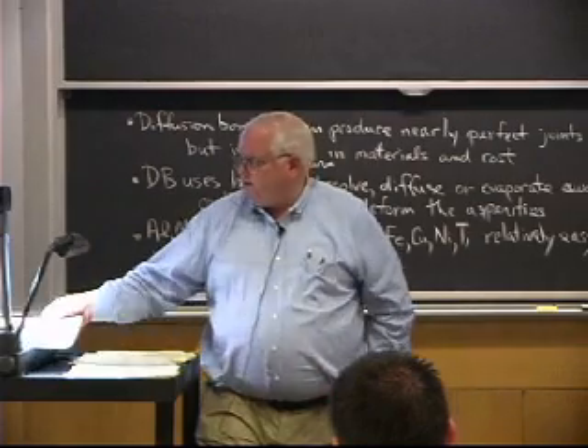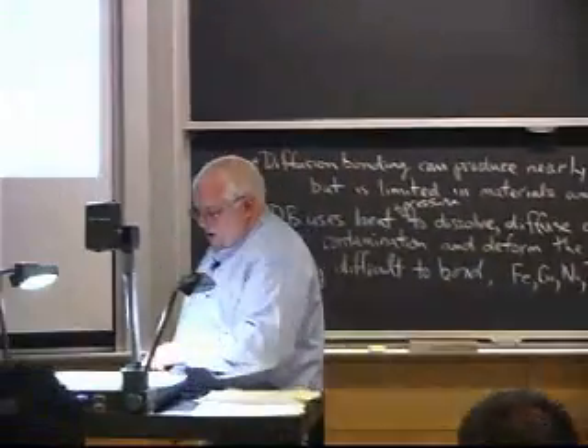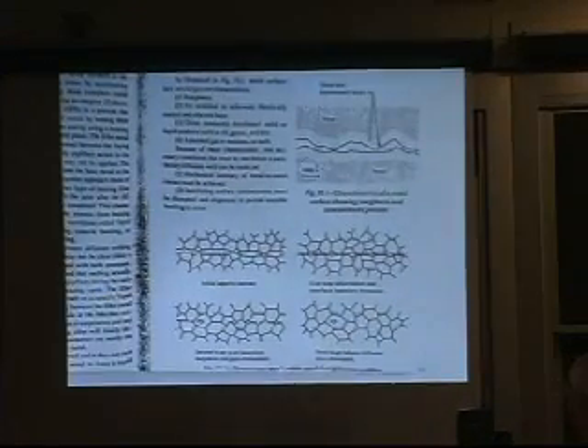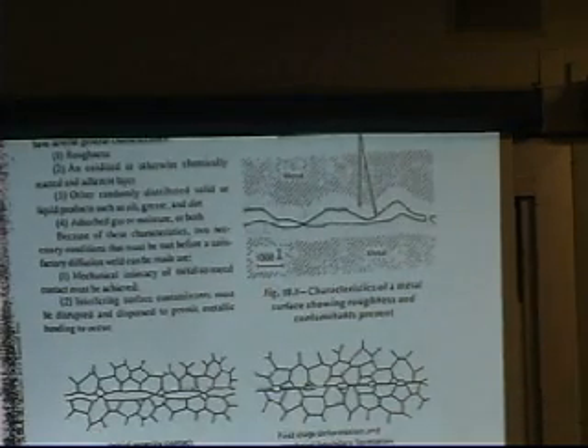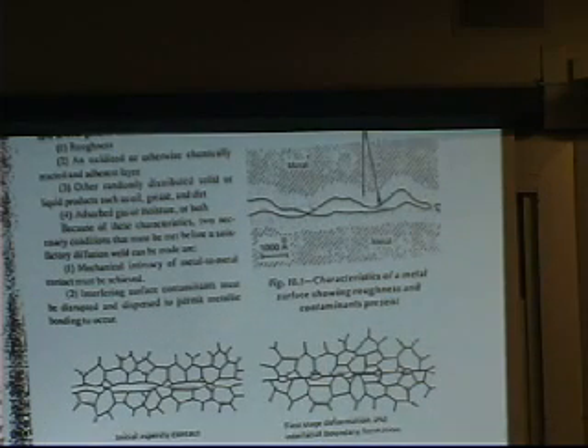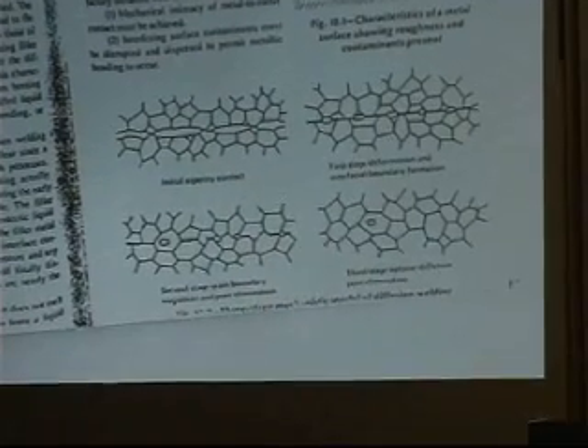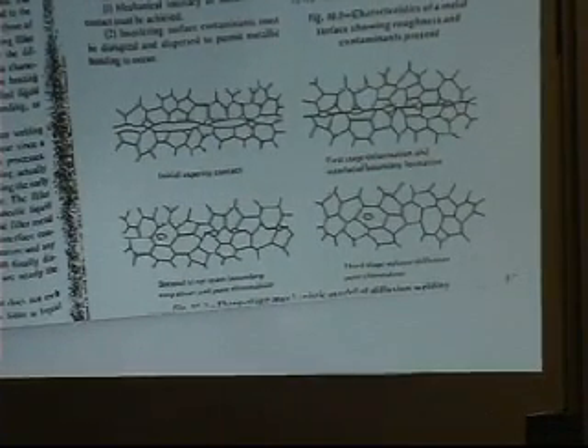Now, how does diffusion bonding occur? Well, this is a nice little cartoon. You've got copies of it in your handouts. It comes out of the welding handbook. Basically, this is supposed to be showing you the asperity contact between two metals that are coming in contact. They're trying to give you a dimension here, so that's 100 nanometers. It's not a very large dimension. So you're talking a very finely polished surface, but on an atomic scale, it's very rough. Well, what happens is you squeeze those together, you'll have contact at the asperities, and this is called stage 1 for stage 1 diffusion bonding.